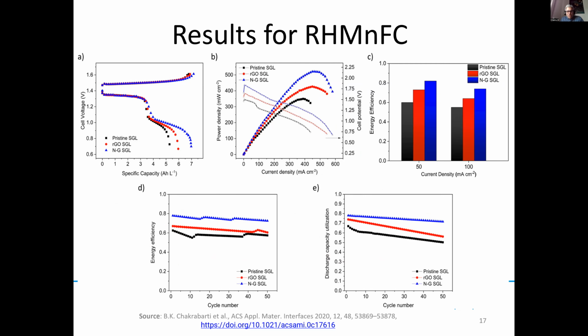But using manganese on the positive side of the hydrogen manganese system has its own challenges, because manganese 3 precipitates at a certain potential and then reduces the amount of manganese available for electrochemical reactions. To prevent this from happening, we use a soluble titanium salt, which forms a complex with the manganese, and then allows the manganese 3 to stay within solution and be utilized as much as possible for the hydrogen manganese system.